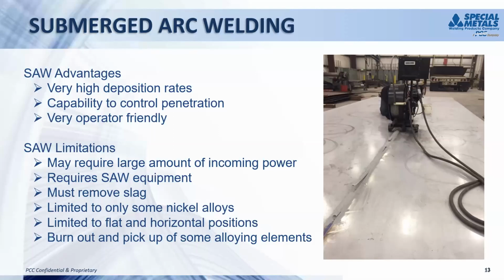The one caution I will point out, and this goes for shielded metal arc welding as well, is any nickel alloy that's relying on a precipitation strengthening mechanism, such as a gamma prime or gamma double prime. You may run into some problems trying to use any kind of flux-based weld process because the aluminum and the titanium, which are really forming those strengtheners, have a very high affinity for oxygen, and they tend to end up in the slag as opposed to staying in the weld metal. So you can lose a lot of those goodies, if you will, the aluminum and the titanium that provide the strengthening from the gamma double prime.